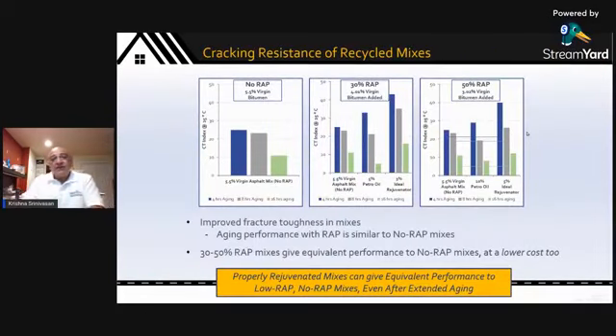So far, we've talked about performance as immediately made in a lab. I want to take you one step further. And what we're doing here, again, a busy chart, I'll try to explain it in as few words as possible. What we're measuring is CT index, fracture toughness or crack resistance, fatigue resistance of a product made with case 1, no RAP, and about 5.5% of virgin bitumen. These are the properties after 4-hour oven aging, after 8-hour oven aging, and after 16-hour oven aging.